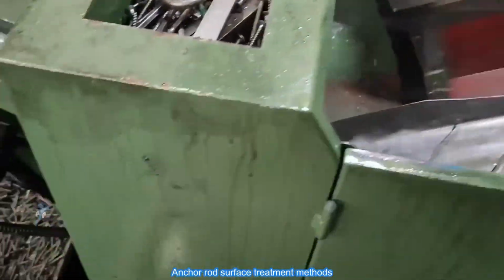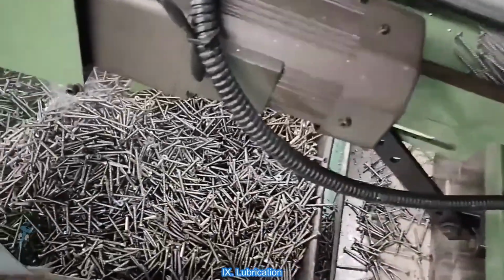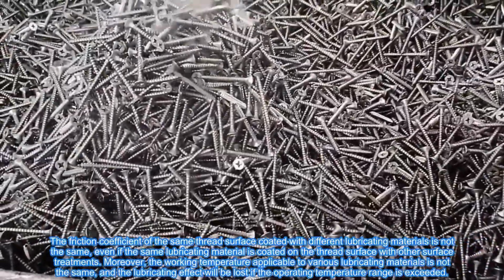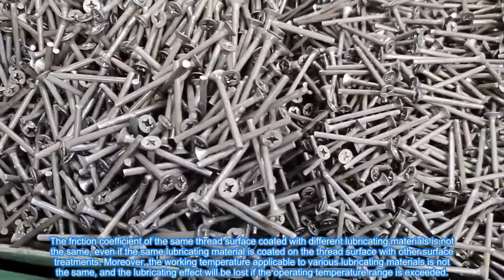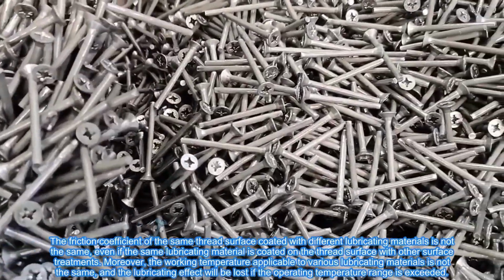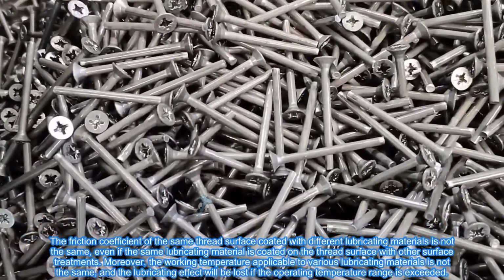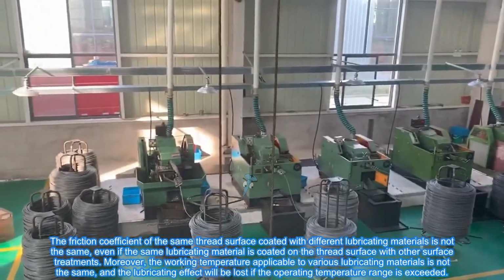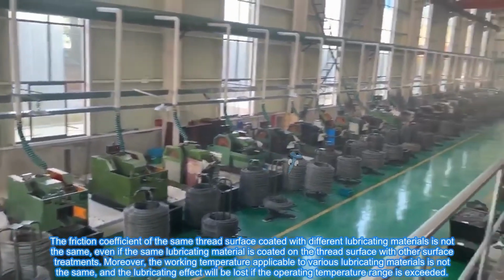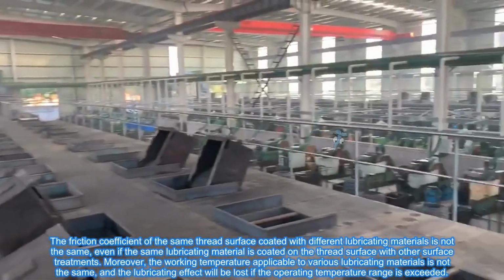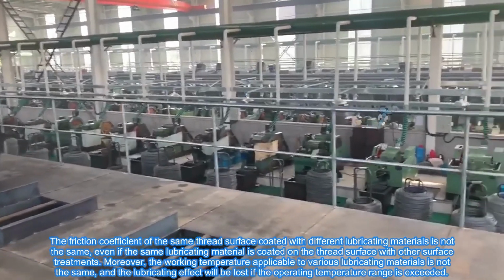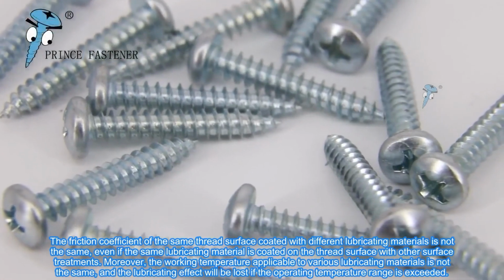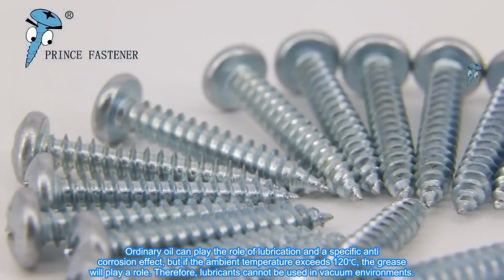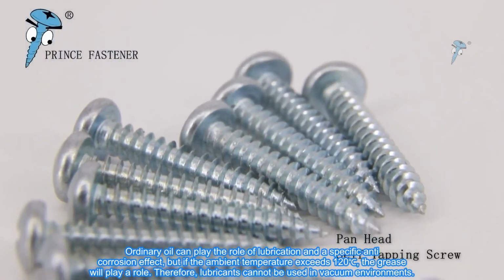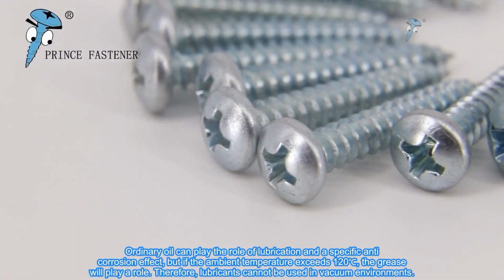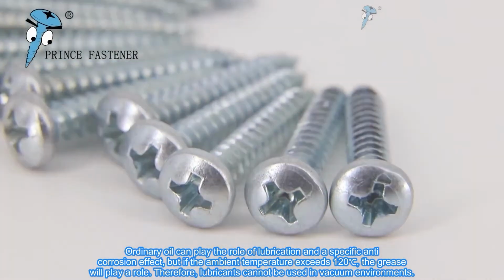9. Lubrication. The friction coefficient of the same thread surface coated with different lubricating materials is not the same, even if the same lubricating material is coated on the thread surface with other surface treatments. Moreover, the working temperature applicable to various lubricating materials is not the same, and the lubricating effect will be lost if the operating temperature range is exceeded. Ordinary oil can play the role of lubrication and a certain anti-corrosion effect, but if the ambient temperature exceeds 120 degrees, the grease will fail. Therefore, such lubricants cannot be used in vacuum environments.